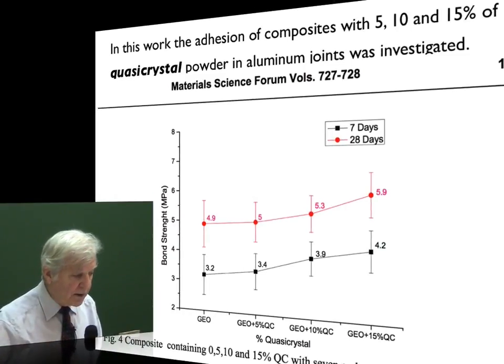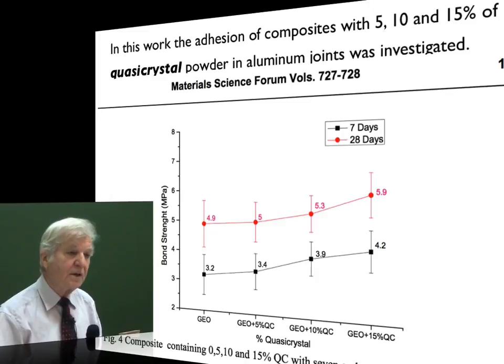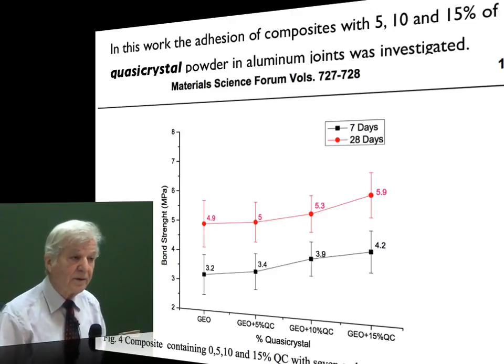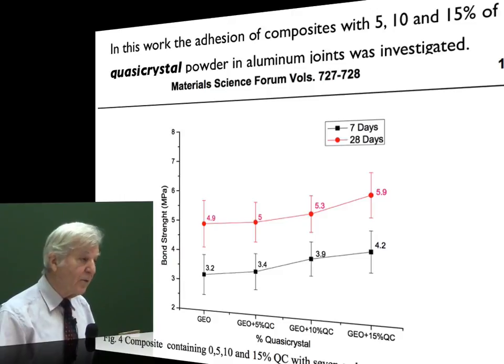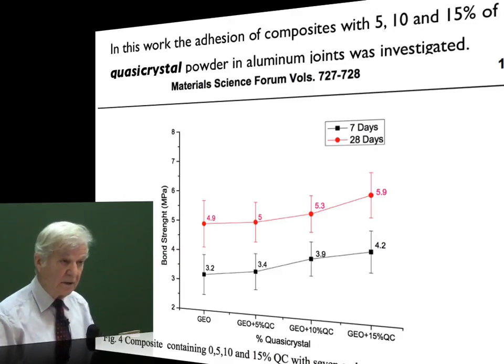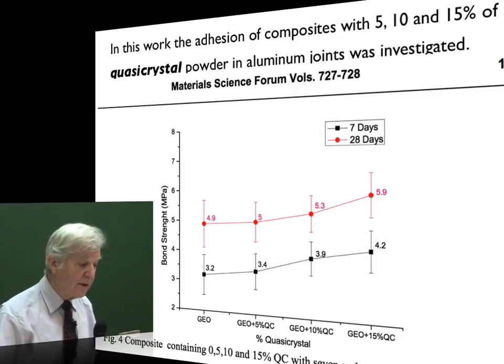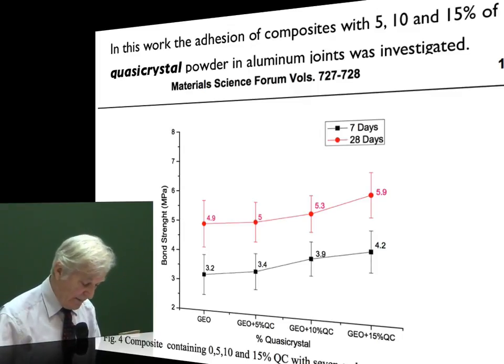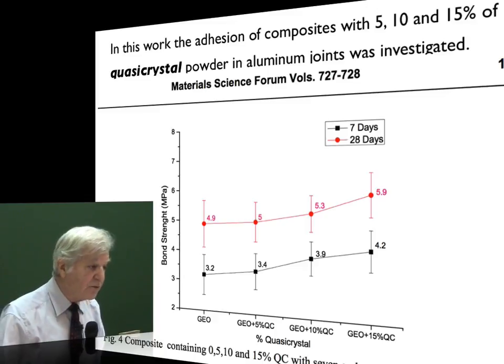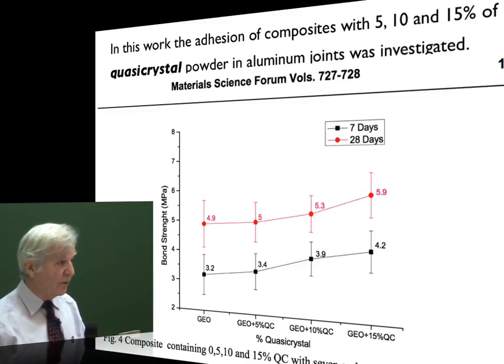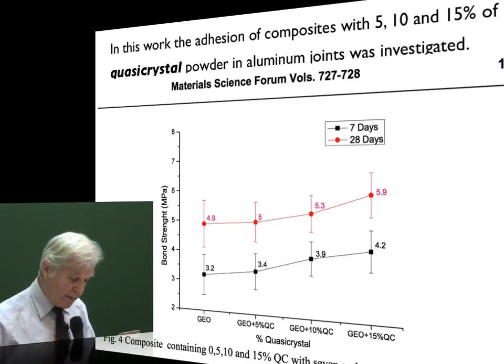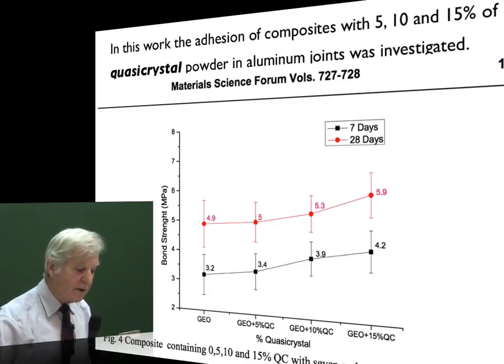I communicated with them, and I thought, well, by introducing an aluminum compound in the system, we know that aluminum is very dangerous. It reacts with the alkali and produces hydrogen, and it is a way of making foam. And they said, no, we don't have any bubbles, we don't have any foams, which means then that the aluminum in the quasi-crystal is trapped, is no longer a subject of any reaction. I was interested in this paper, first for the performance, but second for something totally different.